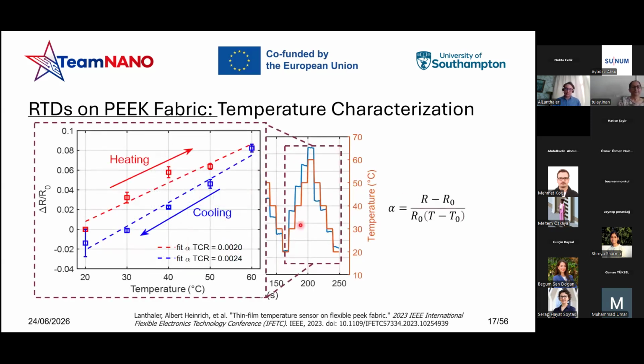So we tested it under temperature characterization for 3 cycles from 20 up to 60 degrees Celsius, in steps of 10 degrees. It shows some reliability, although not precision and accuracy. To avoid any sort of non-linearity and hysteresis effect, I calibrated the sensor from the last cycle. So after 3 cycles, I collected the mean and standard deviation from each step, and I was also able to extract the fitting coefficient of the fitting curve of the measured points. As you can see, the temperature coefficient of resistance, or TCR, is comparable with literature for the same thickness of deposited copper layer.